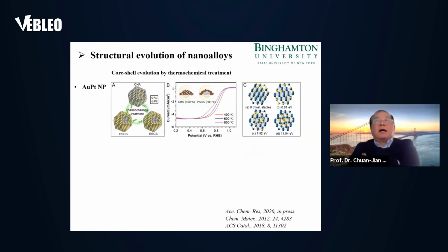Now, before I show you in situ operando data, I want to show you a set of data using thermochemical treatment of nanoparticles. Starting point is a bimetallic noble metal nanoparticle, gold platinum. In this particular nanoparticle, the two metals are not subject to de-alloying, so they're very stable. The stability allows us to study the activity and the structural change. And the one thing illustrated in the middle is that when you raise the temperature to 800 degrees, the gold enriched on the surface forms a core shell structure, and the catalytic activity drops.